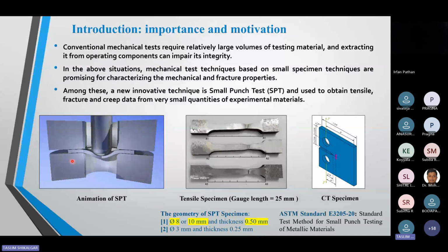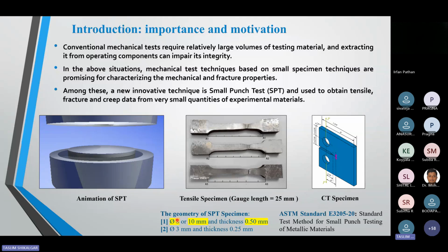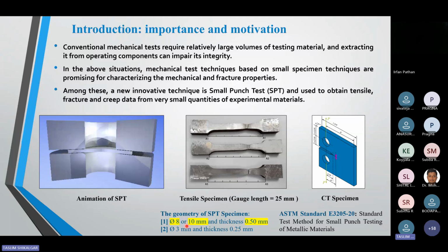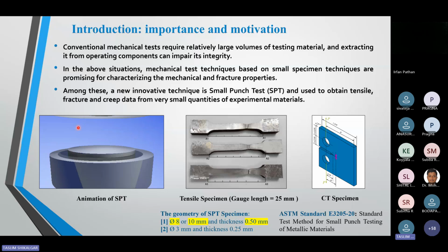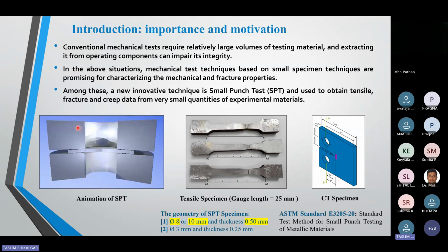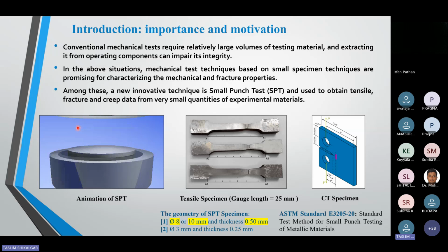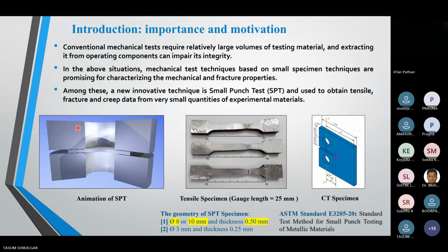This animation shows the small punch test. A disc-type specimen having 8 mm or 10 mm diameter and 0.5 mm thickness is fixed between upper and lower dies, and a punch comes to deform the specimen. With the help of this deformation, we get experimental data, that is, load versus displacement data. Many researchers use this data to get the mechanical properties.